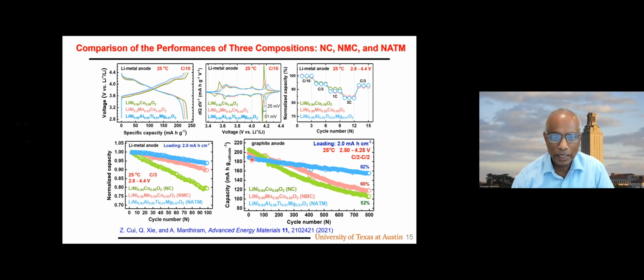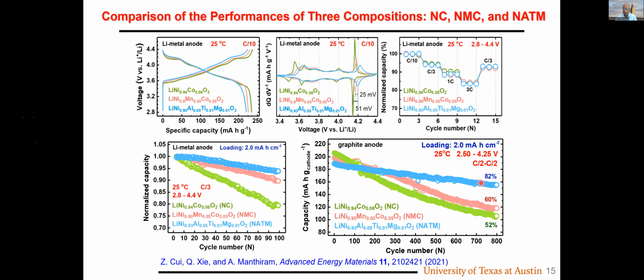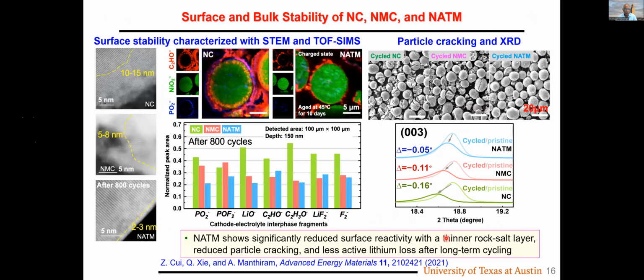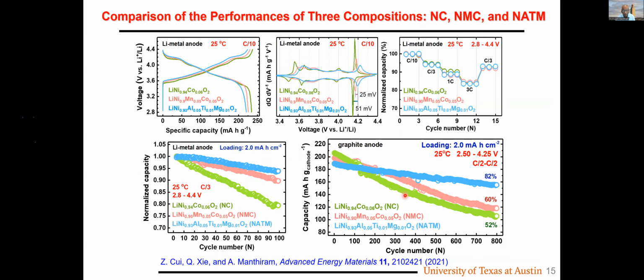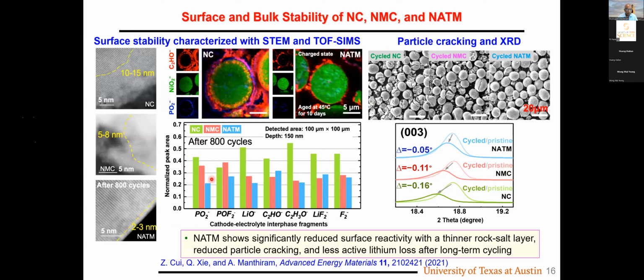To avoid that, we have used graphite as an anode, 800 cycles. Clearly, the NATM shows 82% retention after 800 cycles. That's remarkable compared to the other two materials. So the question is, why do these kinds of dopings help to have better cycle life? We have done a lot of characterization of the cycled cathodes after 800 cycles from this cell. First, this is time-of-flight secondary ion mass spectrometry. The green means the layered oxide. The red color on the surface is the CEI, the interface layer formation.